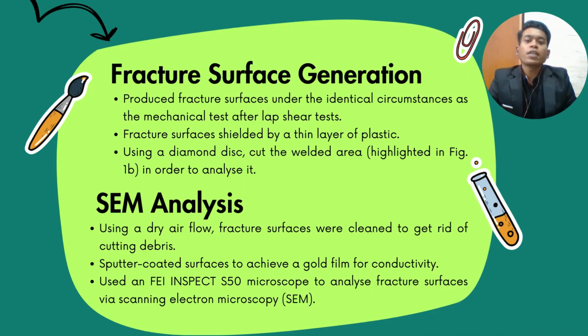Furthermore, fracture surface generation. Produce the fracture surface under the identical circumstances as the mechanical test after the lap shear test. Fracture surface shielded by a thin layer of plastic. Using a diamond disc, cut the weld area in order to analyze it.